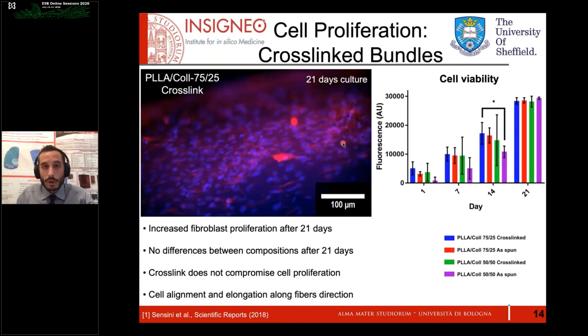We tested, in collaboration with the University of Sheffield, with Professor Gwendolyn Riley and Dr. Liam Boyle, the cell proliferation on our polylactic acid and collagen blends in different percentages, before and after cross-linking. What you can see from this fluorescent microscopy image, after 21 days of culture on the 75-25 cross-linked blend, is the human fibroblast nuclei stained in blue, elongated along the direction of the red nanofibers in the background.